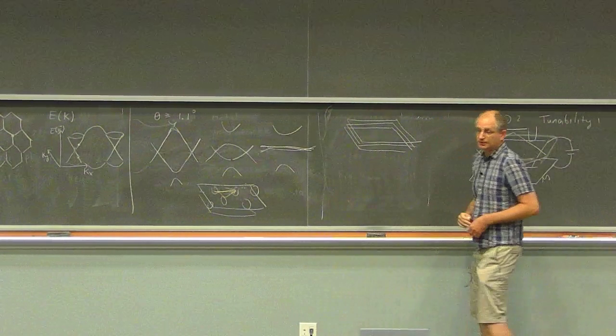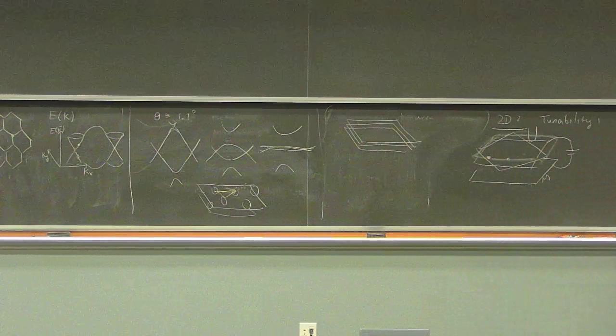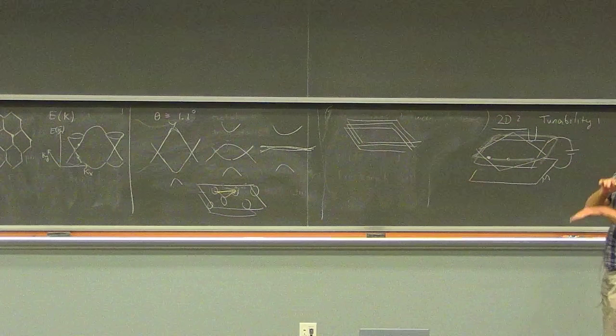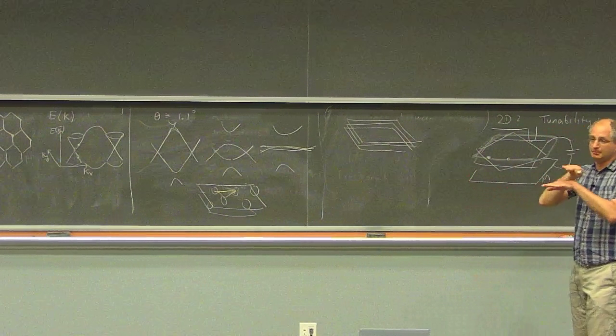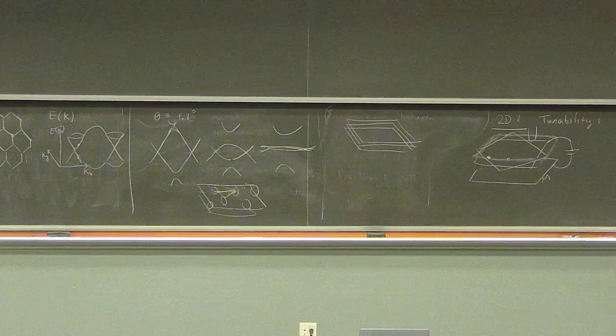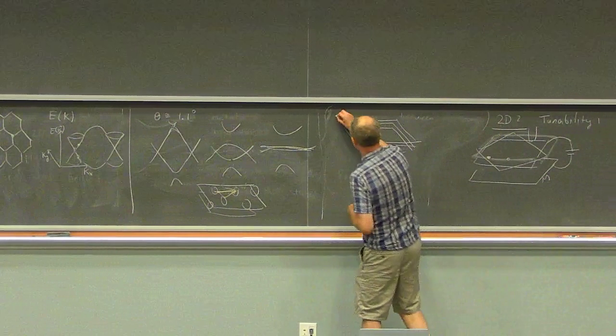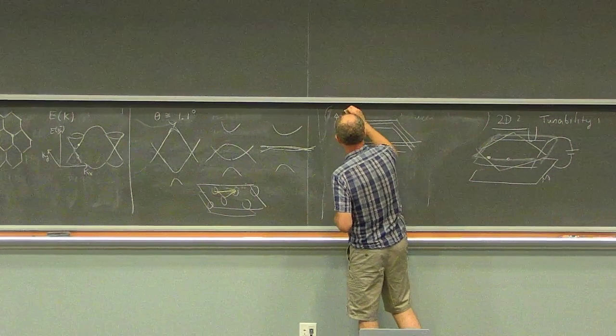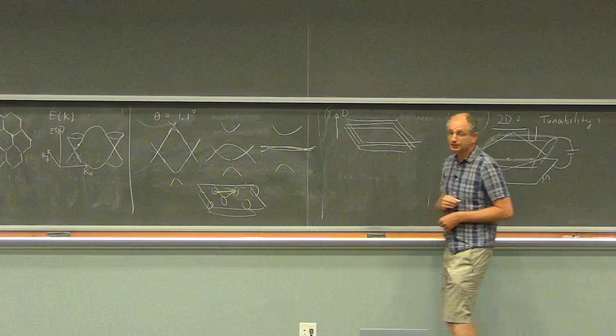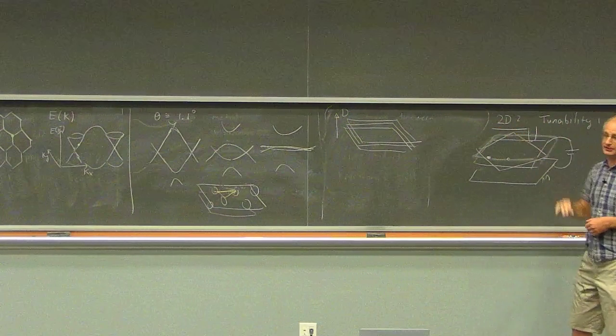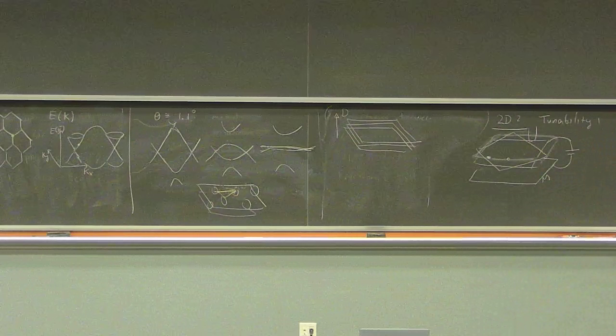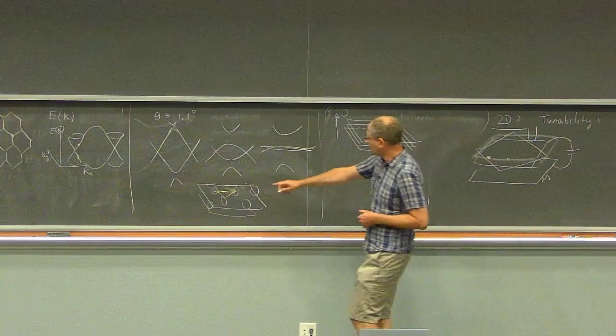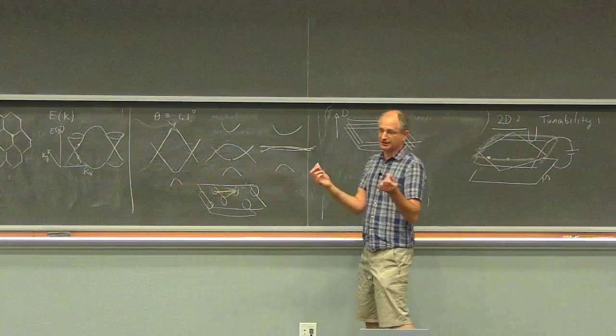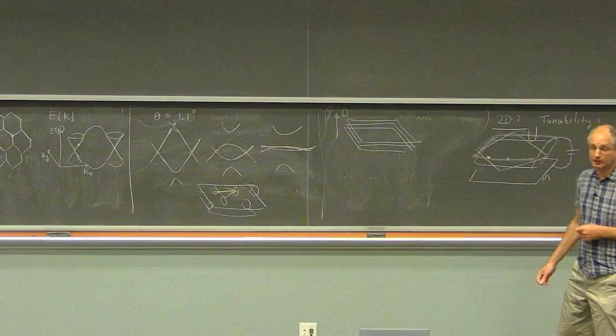Okay, so you find graphene sheets that are not aligned in a natural way, or aligned in a metastable configuration, and then apply a strong electric field, a perpendicular displacement field, which polarizes the electrons mostly to one of the layers. So now there's no Moiré lattice, there's no big length scale. The only length scale in the problem is the distance between carbon atoms.